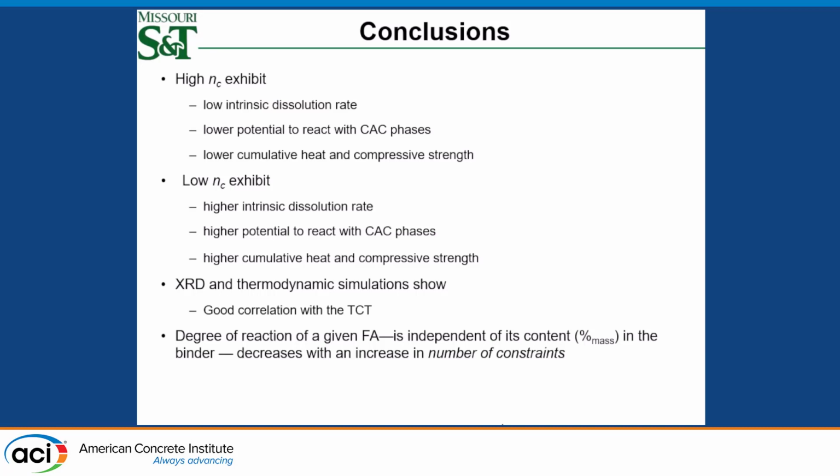Whereas for low NC, it's completely opposite, because you have a sufficient amount of silicate ions being released to react with anhydrous phases and hydrate phases to form stratlingite and other components. From the thermodynamic phase assemblage and XRD, we clearly showed how it has a good correlation with the TCT theory. And finally, we would like to say that the degree of reaction of fly ash is independent of the replacement level. And as the NC is increasing, the fly ash reactivity is decreasing.